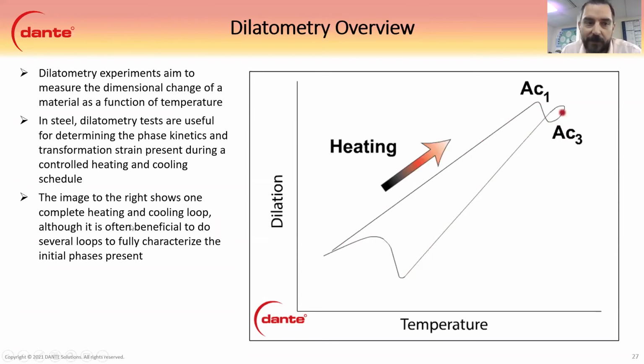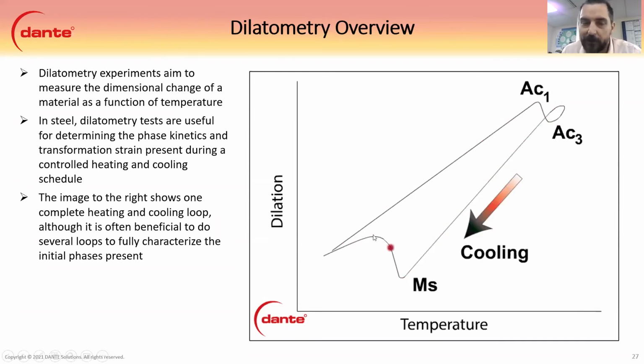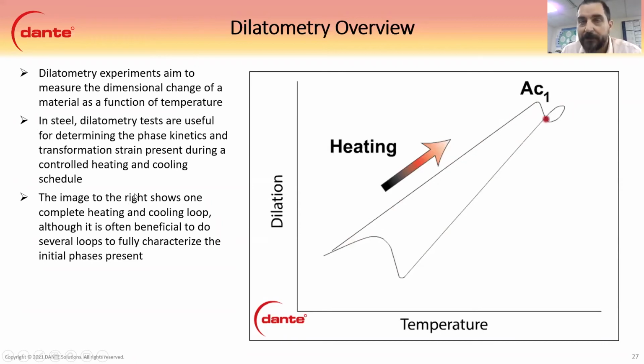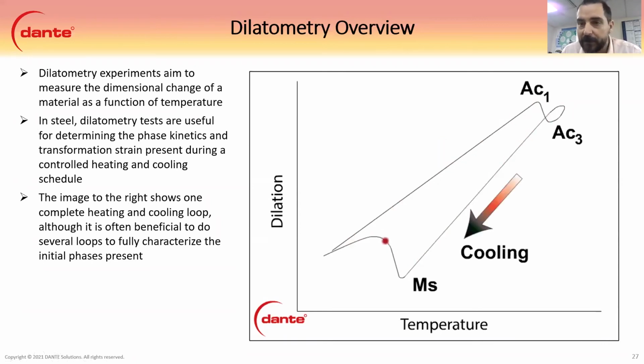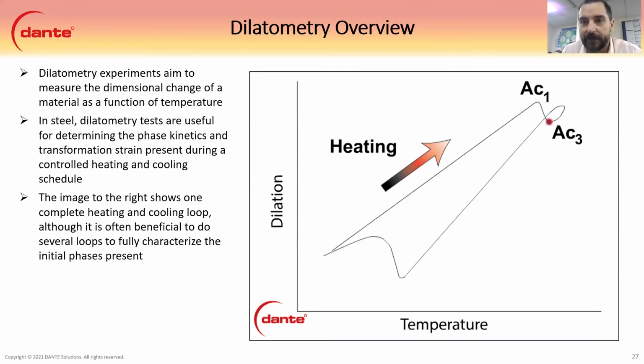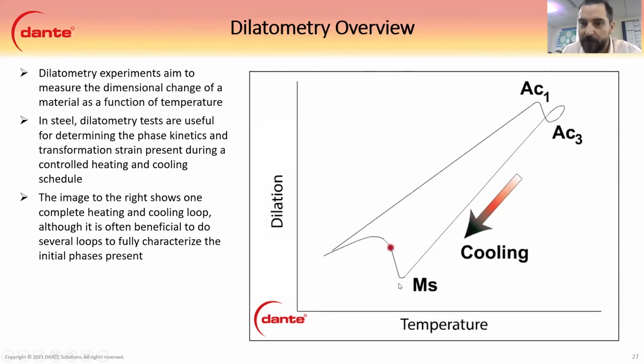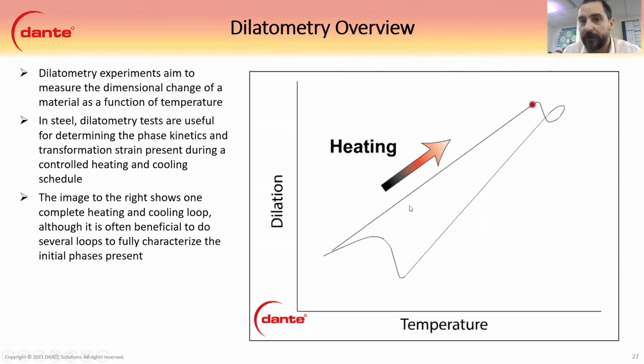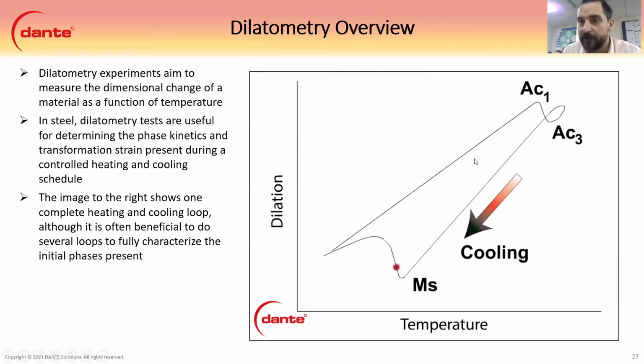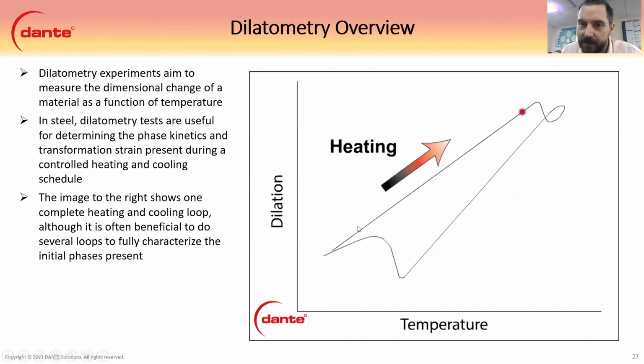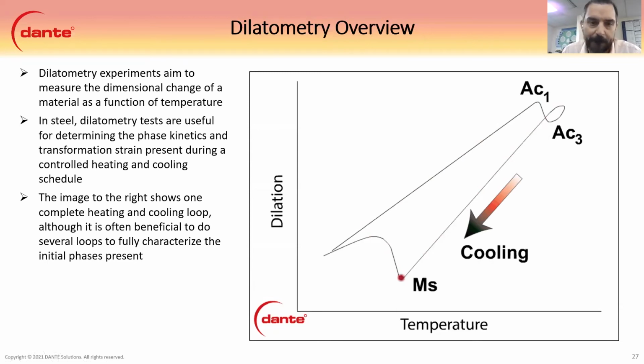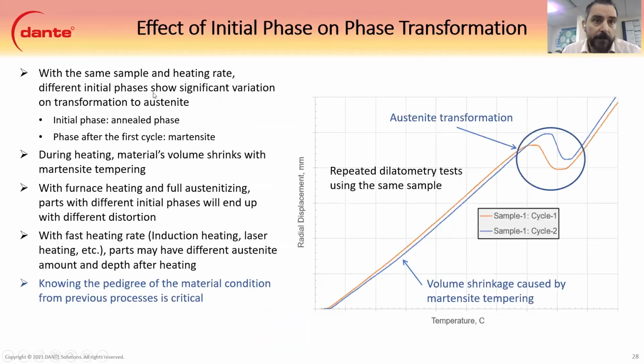And then this shows one loop over and over again, but you'd probably do several loops in order to fully characterize the base material and everything there. So the next loop would be all martensite, and we would know that would change the shape of this curve a little bit, because each one of these phases has a different coefficient of thermal expansion. So with the same sample and the same heating rate, the different initial phases cause a significant variation here.